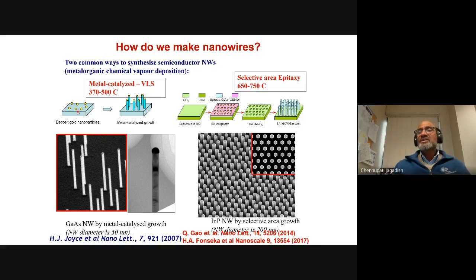And then it turns out the gold has a melting temperature of more than 1000 degrees Celsius. But once the gold starts reacting with the gallium or aluminum or indium, what happens is that a eutectic forms. That means the alloy has a much lower melting temperature than the individual component melting temperatures. For example, most of these alloys of gold gallium, gold indium, and gold aluminum have a melting temperature of about 350 degrees Celsius.